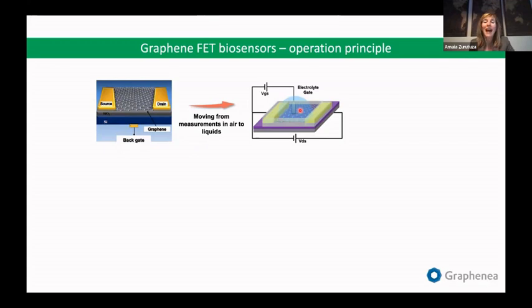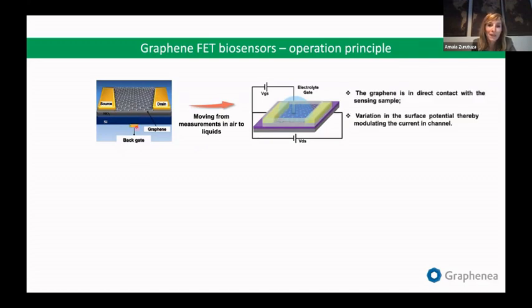And when we have a solution containing ions, graphene is capacitively coupled to these ions, forming an electric double layer. So this electric double layer is like the oxide in the back gate configuration, right? And this means that when we have these ions, the graphene is really, really close to the sensing event. And that's why we can make very sensitive biosensors.